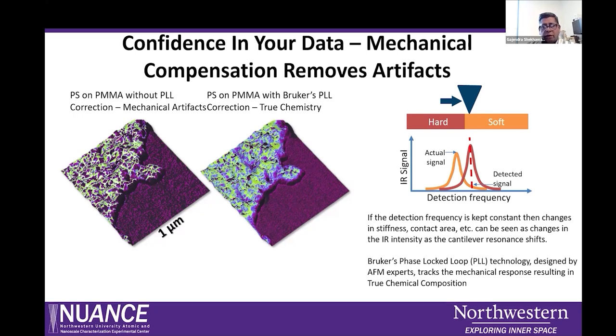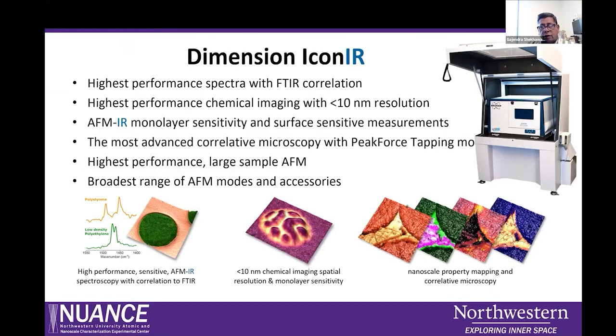On the left, you can see the image without the phase locked loop, and on the right, which is a much cleaner, nicer image, is with the phase locked loop, which represents the true chemistry of this imaging technique. The Dimension IconIR we have is pretty much the AFM that you are using. It's an 8-inch stage here, but it's exactly the same, with high performance spectra with FTIR correlation. You can go down to even 5 nanometer spatial resolution, and also spectral resolution in the case of tapping mode IR. It's monolayer sensitive. And you can also do correlative microscopy. That's one of the advantages here.